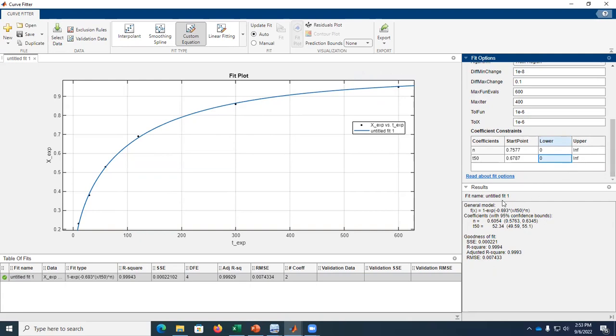And in the upper limits, for example, if we still have some problems with fitting the data, we can narrow down the upper limit a little bit more. So for example, I know that N is usually an exponent that goes from 0 to 1, so I don't need to go to infinity. I can just use 0 to 1. Obviously here it is the same result. And this other upper limit could be infinite as well, which is too large, so I could put a large number, for example, 10,000, something like that. So basically it's fitting much better.